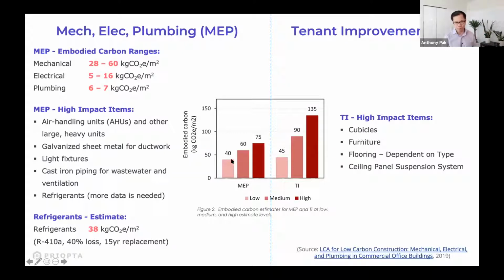And so there's different ranges of estimates. In this case, it's from the Carbon Leadership Forum, they did a study. They estimated between 40 to 75 kilograms of CO2 per meter squared. I've seen some studies from Integral Group that have gone up to like 2 to 300 kilograms of CO2 per meter squared, depending on the facility. So it can get quite high.